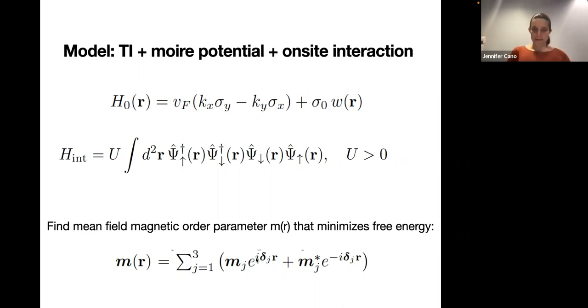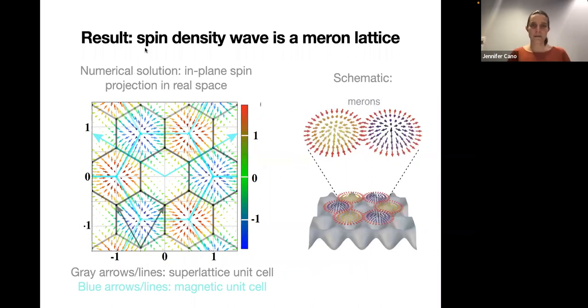There's actually a large space of such parameters because there are three different possible wave vectors. And for each wave vector, there are three different spin orientations, which are parallel, perpendicular, or out of the plane. So there's in total a nine-parameter space, and we're trying to find the order parameter in that large space of possibilities that will minimize the free energy. And so the result that we found is actually even more surprising than we imagined. The resulting spin configuration that minimizes the free energy forms what we call, or I think what's called, a meron lattice. So let me say something about how this works.